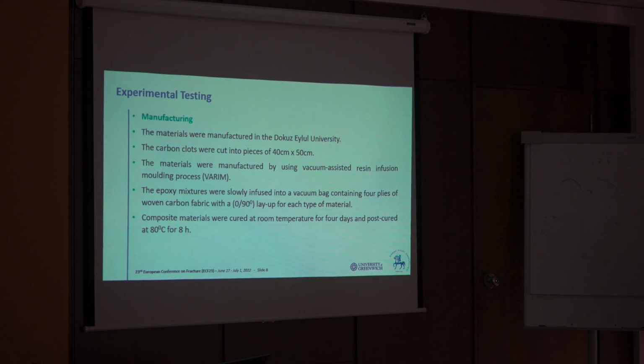After manufacturing them in Turkey, as I said, we ran the experiments in the UK. So basically we started to manufacture small pieces rather than big ones in order to learn how to deal with the liquids, or the carbon nanotube ones actually. The perfect size for us was 40 centimeters by 50 centimeters, and again all the manufacturing included the vacuum infusion technique, and the epoxy mixtures were slowly infused into the vacuum bag every time, and for each specimen we used 4 layers of carbon cloth.